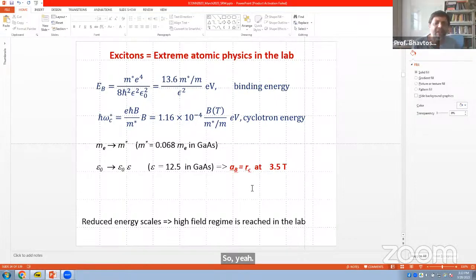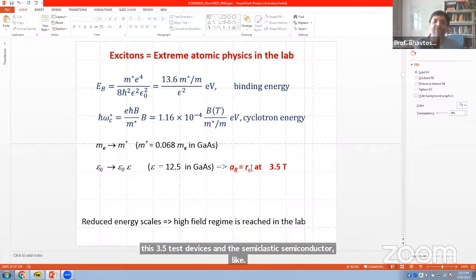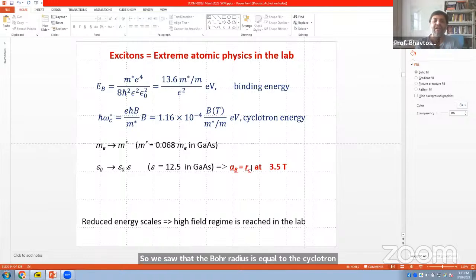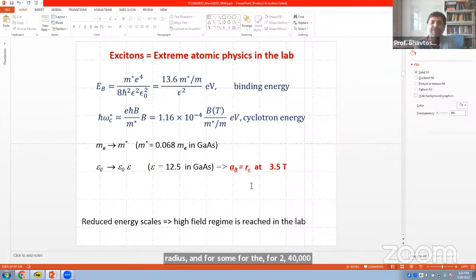So this is again something which I had already said. In semiconductors, on account of larger dielectric constant and smaller mass, the field scale is much lower. For instance, we saw that the Bohr radius is equal to the cyclotron radius at 240,000 Tesla for a hydrogen atom, and this becomes something like 3.5 Tesla for gallium arsenide. So already at 3.5 Tesla or so, you start to see strong field effects, and that's why laboratory scale magnetic fields of this order can be useful.